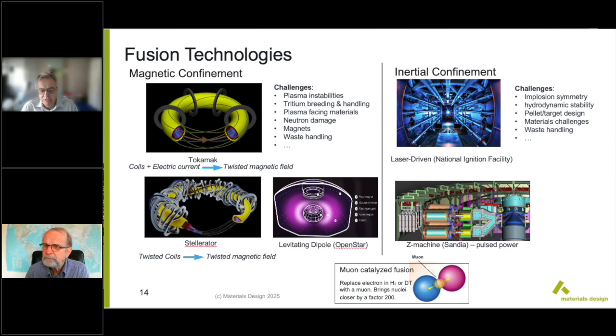And as a design principle, when you consider metals and, for example, in alloys, it is something very much to be considered to make sure that the lifetime, the radioactive half-life of any potential radioactive isotopes that are getting created is not too long. And at the moment, mostly those requirements are being satisfied. But there is, that's why I said there is, of course, still some problem with radioactive waste. It's significantly less, or much, much less than for fission reactions or reactors.